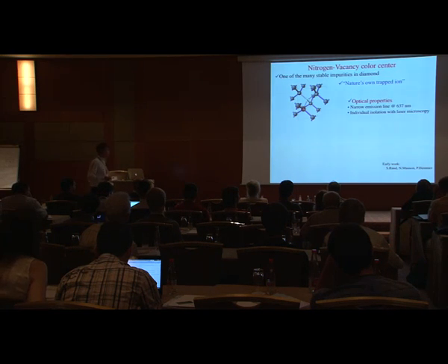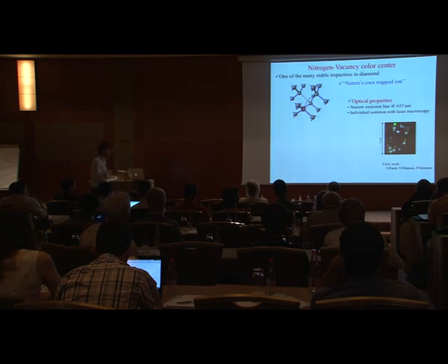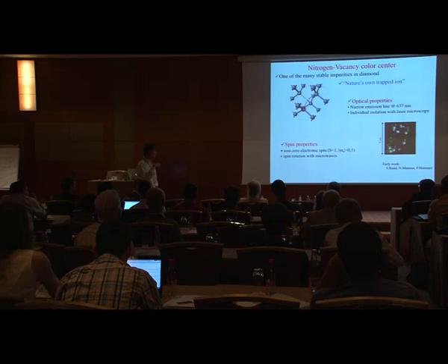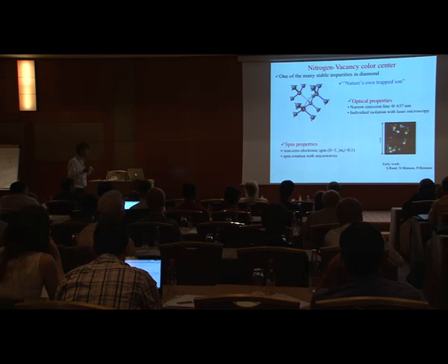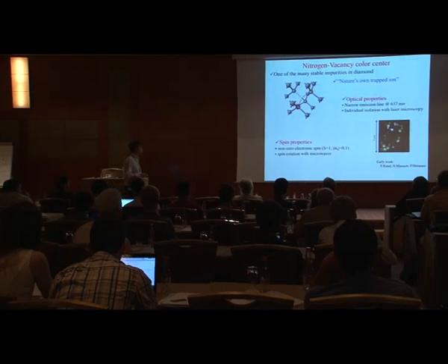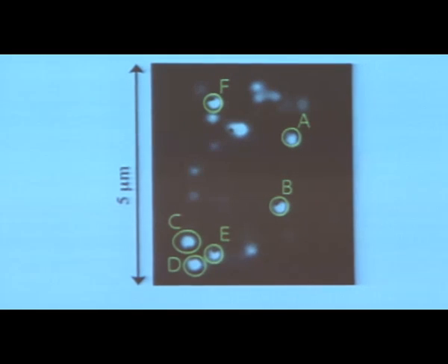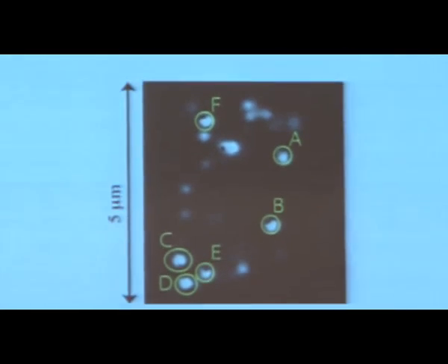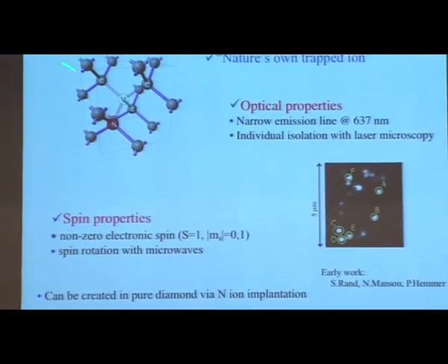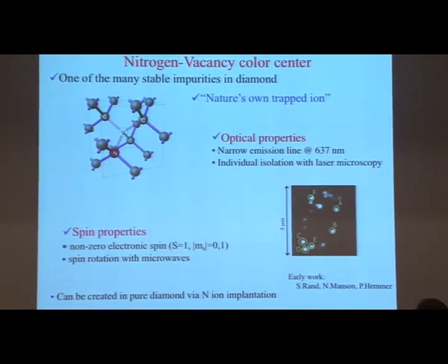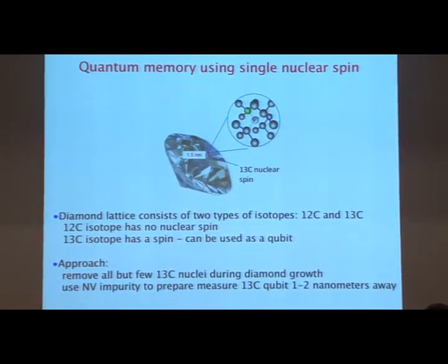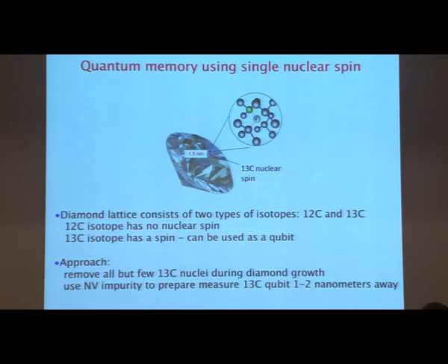It has suitable optical properties. For example, by using laser microscopy, one can isolate single atoms. So this is a microscope image where these little dots are single nitrogen vacancy centers. It also has this magnetic spin degree of freedom, which I already mentioned. It is in fact a spin triplet, so it can be rotated with microwaves. Most importantly, these nitrogen vacancy centers can be created in pure diamond by implanting nitrogen ions and then annealing the sample to create stable centers which can exist forever. So the idea of making a memory is very simple.